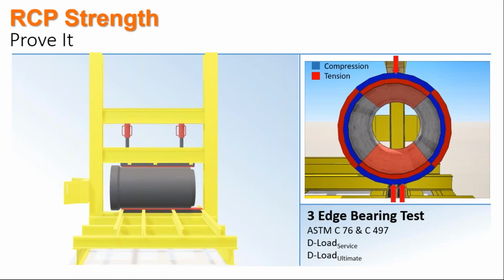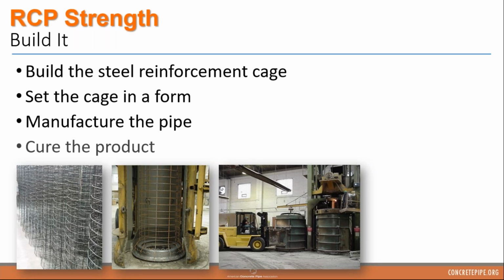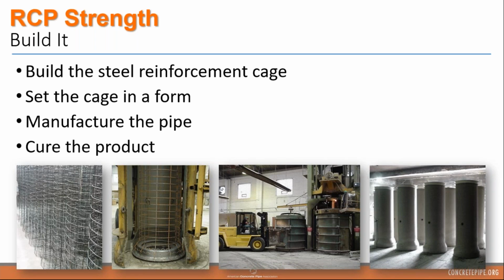So let's shift gears slightly and look at how that strength is built into reinforced concrete pipe. First, as we've already mentioned, the reinforcing cages. These are always built on site at the plant for each specific class of pipe. The cages are then set on a bottom pallet, which forms the interior of the bell, and then the outer jacket closes around the cage. Then this pipe is produced either through the vibratory process or through the packer head process, and we'll talk about both of those in a second.